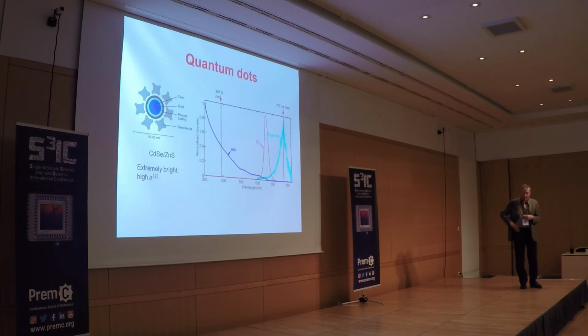All right, so it turns out that with single molecules, the experiment is actually very difficult. We still hope to do it in the next months or years, but it's quite difficult. The reason is that although the enhancement factor is very large indeed, the process itself, to begin with, is very weak. So the product of these two things is barely observable. So we decided, let's try to have a demonstration. That was, again, Wei Chun's idea. Let's try to do a demonstration experiment with something which has a much larger two-photon absorption cross-section than a single molecule, a quantum dot. And this is what is done here.